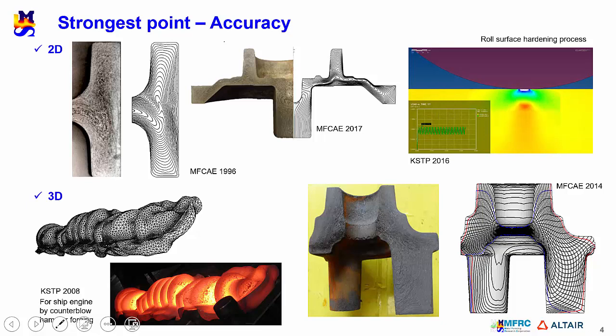I'm going to show you some selected examples which can imply the accuracy of our predictions. The upper three are for 2D and the lower two are for 3-dimensional. These three examples compare the predictions with experiment in terms of grain flow. They are quite good. This compares the response of oscillatory force due to roll oscillation during a special roll surface hardening process. This compares the shapes of experiments and predictions. All comparisons in this slide show the accuracy of AFDEX. We have made numerous comparisons between our predictions and experiment, which can be found on our homepage.